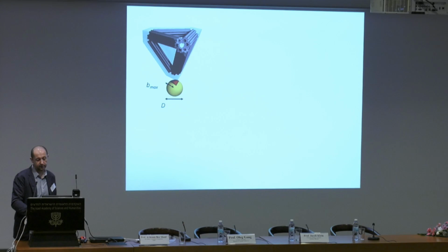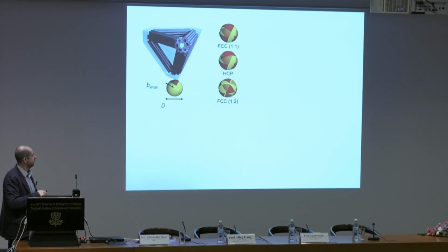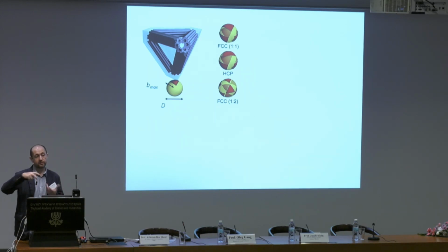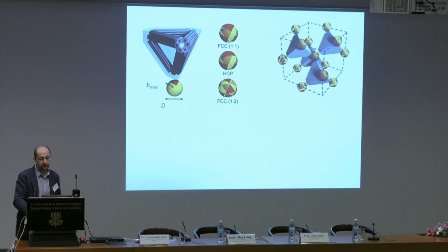However, this triangular footprint allows us to look at what the size of the footprint is in comparison to the particle. And if you ask what the best arrangement of triangles on a sphere is, you can come up with different types of arrangement depending on the relative size. It turns out that in a certain regime of particle size to footprint, this type of organization would be the most beneficial, the best. And at the same time, since it's a footprint, from 2 dimensions, the positioning of the triangles allows us to orient the tetrahedra in 3-dimensional space.